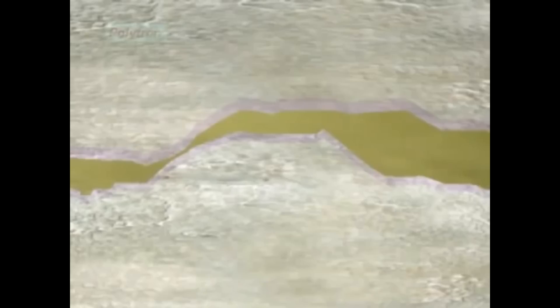Since the protective layer is very thin, it is as flexible as a very thin sheet metal. Although during collisions the protective layer does not allow metal particles to break away, its flexibility allows the metal underneath it to be pushed horizontally by the horizontal force generated by collisions. Thus, the metal on the mountains is pushed into the valleys, flattening out the friction surface, resulting in a smooth, polished-like surface that has a much lower friction coefficient.